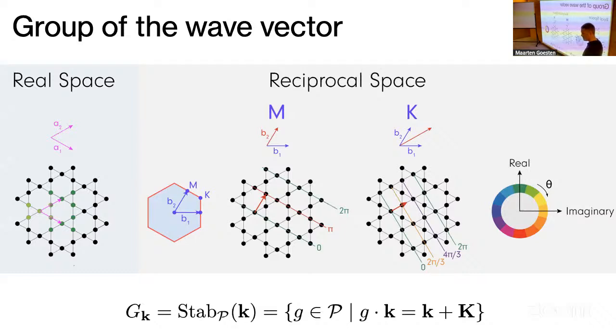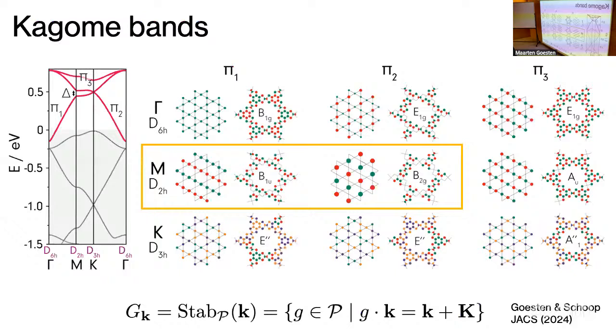Mind that the D3h point group does not have inversion symmetry in the group, okay? So that means that you necessarily get complex phase factors here. And that's what you get when you work this out in terms of the orbitals. What I need you to see here is these two orbitals, B1u and B2g. To distinguish between representations, irreps of point and space groups, I capitalize the space group irreps. For the molecules I have made them small, but these are exactly the same irreps as we had for the molecular case, now with periodically translated versions of that.